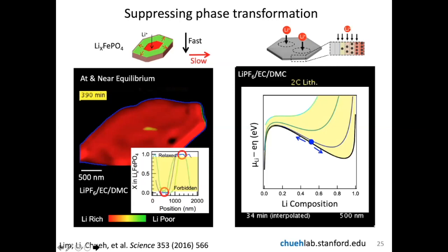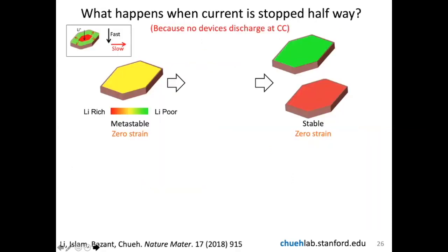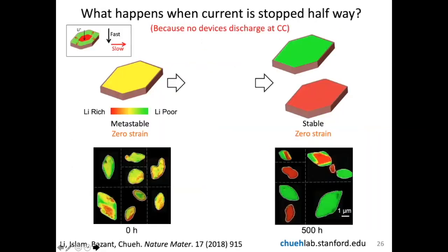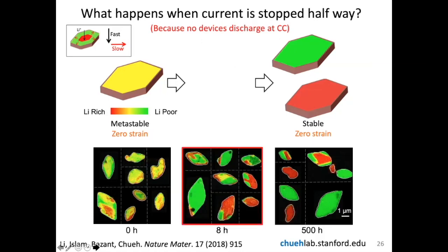So what I'm highlighting in yellow here is the composition dependent overpotential. So when the resistance of the battery is dependent on composition, you can actually cause a phase separating material not to phase separate. In the case of NMC, it's exactly the opposite. So with that, let me just conclude here and then come back to my design rules.